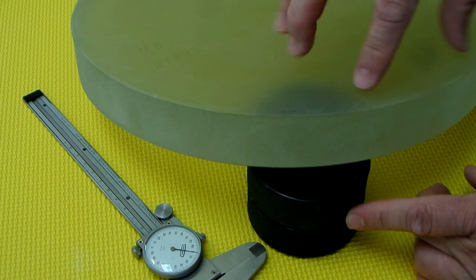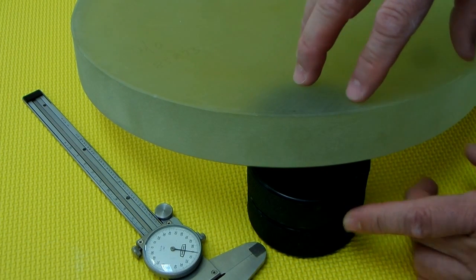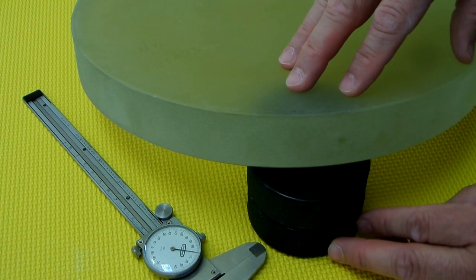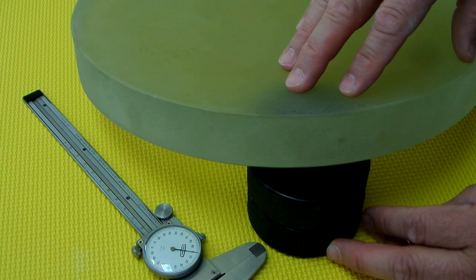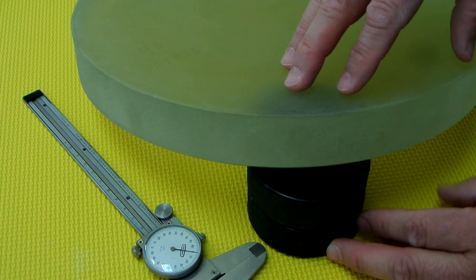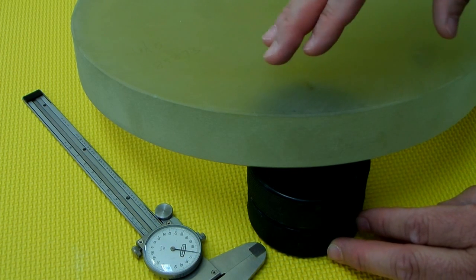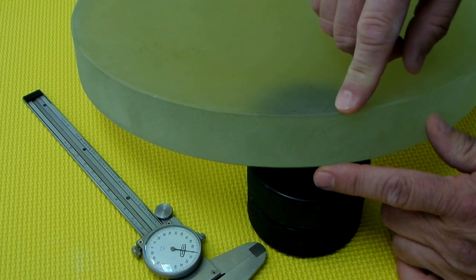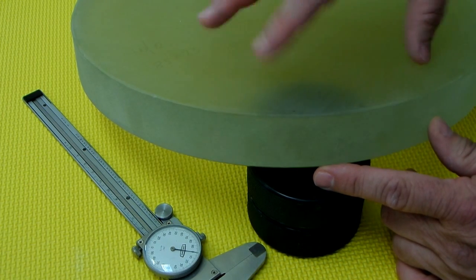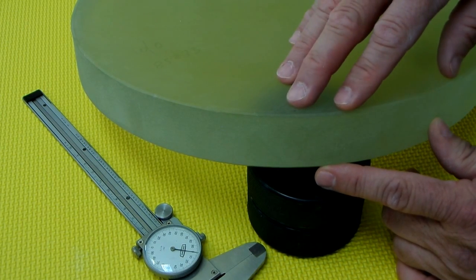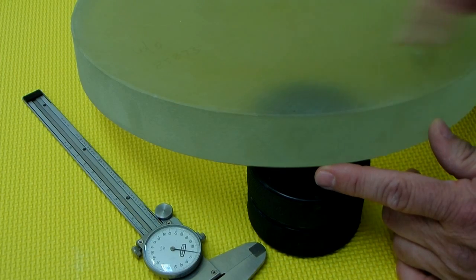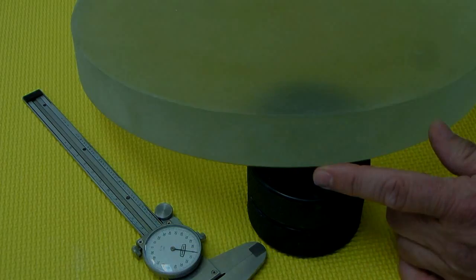The client specified that the edge thickness has to be between 1.339 and 1.417. So we're at 1.425. That's only eight thousandths of an inch too thick. We'll definitely lose that during the process of grinding the mirror out. So thickness looks really good on this one. On to check the curvature that's been generated.